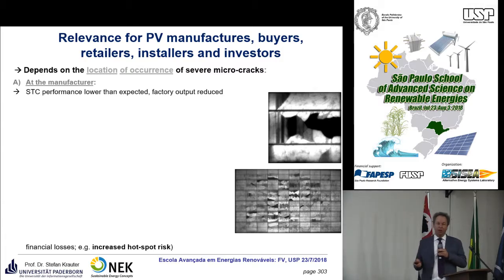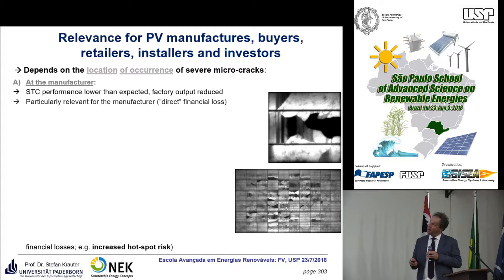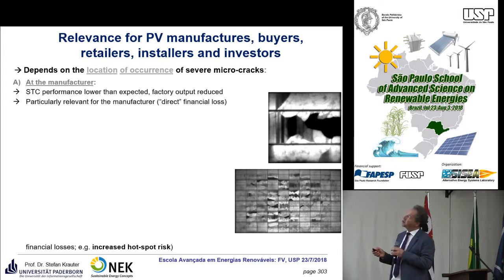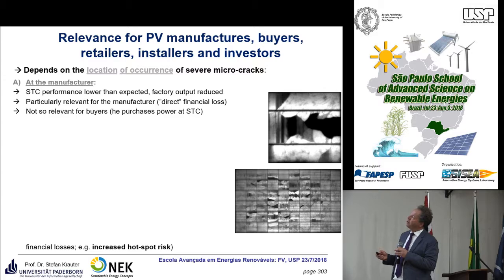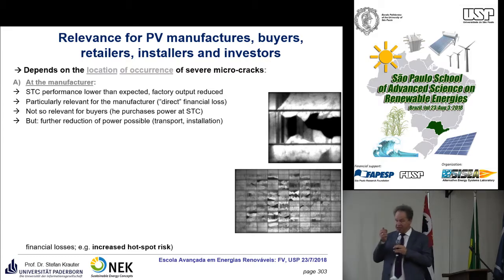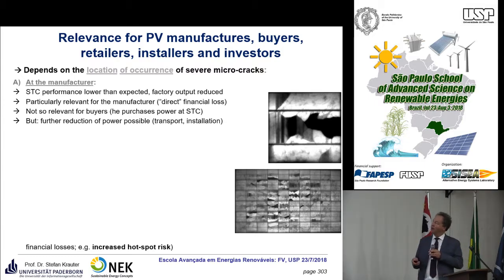For you as a consumer, it doesn't matter so much because you get less power and you also pay less for the modules. Instead of having a 300 watt module, you have maybe only a 260 watt module, at a lower price. So this is relevant for the manufacturer, the direct financial loss, not so relevant for the buyers because you purchase power at STC. But there could be some further reduction in power possible, where these microcracks can propagate and then cause snail tracks and other problems if you do not pay attention to that.